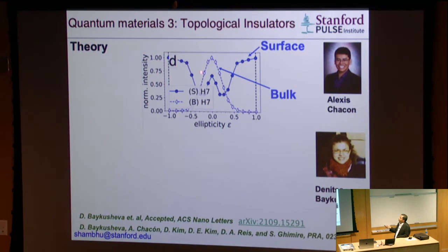The intensity of harmonic drops significantly in the case of the bulk when you increase the ellipticity. When you go from linearly polarized laser to circular polarization, for linear polarization you expected a high intensity, but for the circular polarization nothing for the bulk, right? Because bulk does not have this spin momentum locking. I have to make that clear, which I forgot earlier. The surface, on the other hand, has the highest efficiency for the circular polarization.